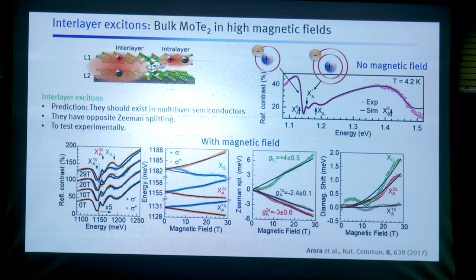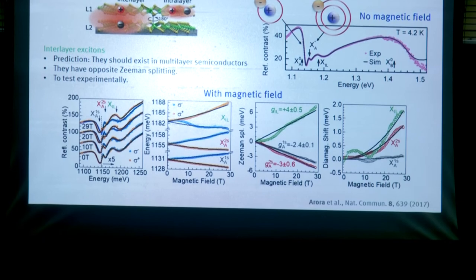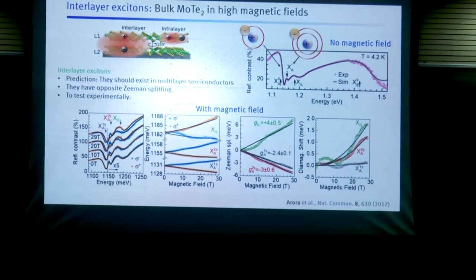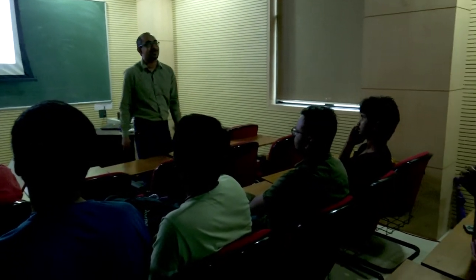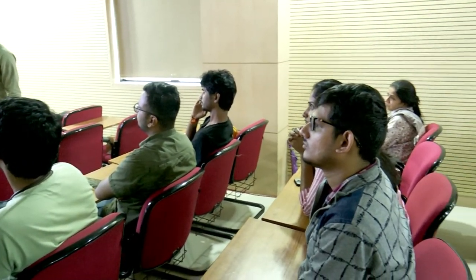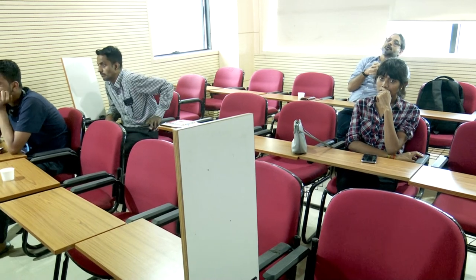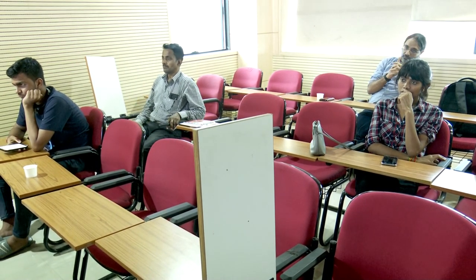Yes? Sorry, I got slightly confused. The interlayer exciton is loosely bound, right? Why is it that its binding energy is comparable to that of the intralayer exciton? In fact, it's more than... No. So, the band gap is somewhere there. This is less strongly bound and this is more strongly bound. And this is a bulk material, so the band gap has already reduced quite a bit. So the binding energy of the interlayer exciton here would probably be half of that of the intralayer exciton.